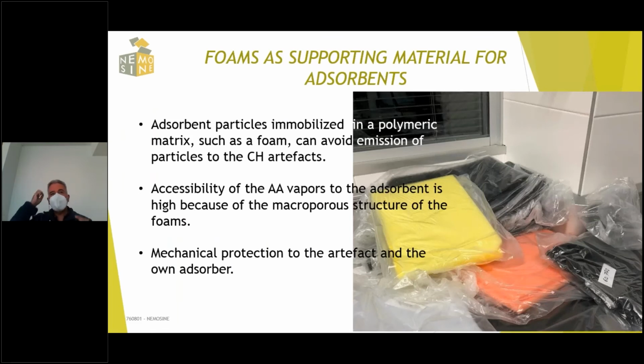Well, I have said that to use or to combine the MOFs, the metal organic frameworks, with a supporting framework is very important. In this case, I would like to focus my training on foams as supporting material for this kind of sorbents. If we immobilize the sorbent particles that we are using in a polymeric foam, we can increase the performance of these materials, or at least avoid important problems that I have commented on until now, such as the pressure drops. It's important to have accessibility of the acetic acid vapors to the sorbent, and the macroporous structure that defines this kind of foams is perfect to have the maximum surface accessible for the gases, for the acetic acid vapors.